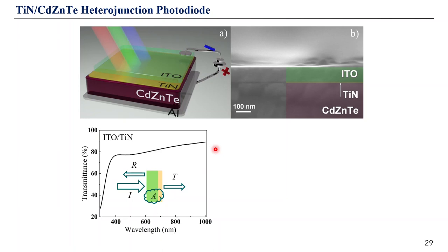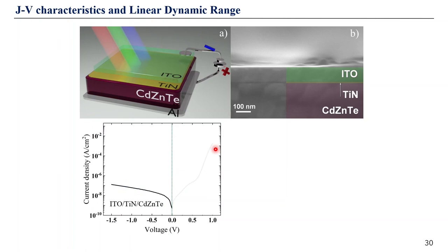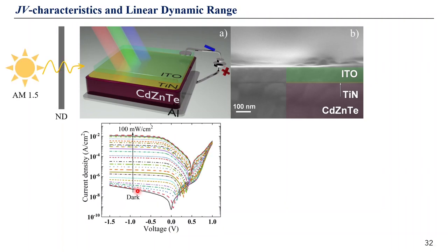Afterwards, it was necessary to check how this heterojunction performs. So we measured a dark IV curve, and here we need to focus, as for a photodiode, on reverse dark current, because that is the parameter which defines the background noise and sensitivity of these devices. And we have shown that the introduction of the titanium nitride layer significantly reduces the dark reverse current in this device structure, and that is really good for high performance photodiodes. So the next step is to check how this heterojunction responds to light.